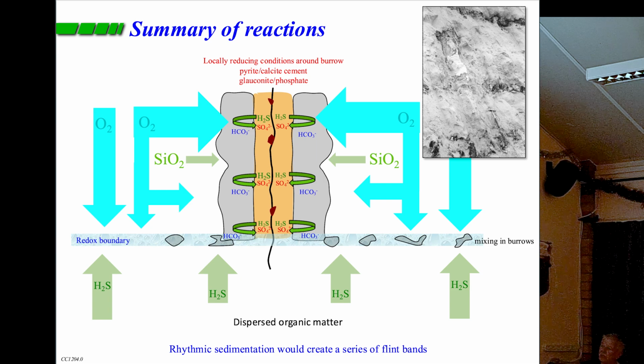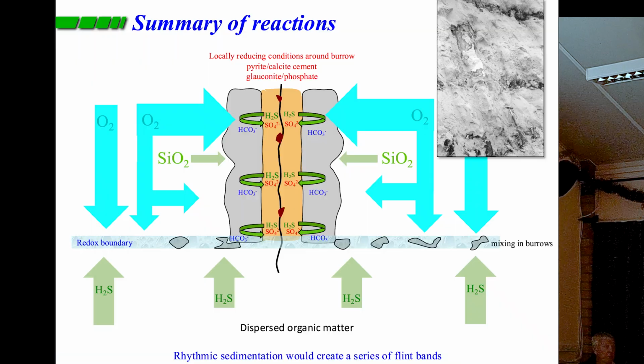Now, there will also be a lot of just dispersed organic matter in the sediment surrounding the chalk, and that will also eventually pass into sulfate reducing conditions. So while this is all oxidized up here, there will be H2S forming down here, which means we have another boundary just through here where oxygenated conditions are juxtaposed with sulfate reducing conditions. So oxygen coming down, H2S going up. The result is we have a mixing zone in there, exactly the same as the paramudra, except it's a horizontal plane, and these two will actually mix in there, so that this will be a horizontal zone of flint formation as well.